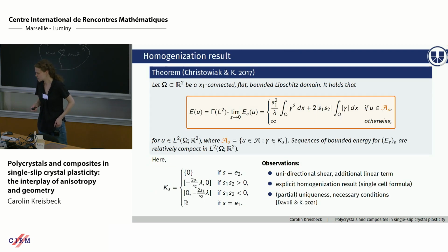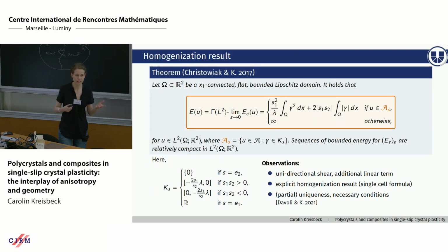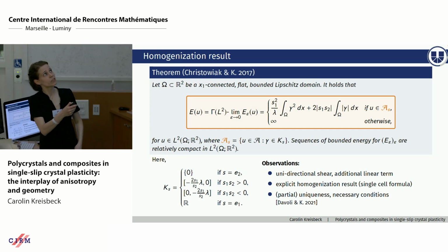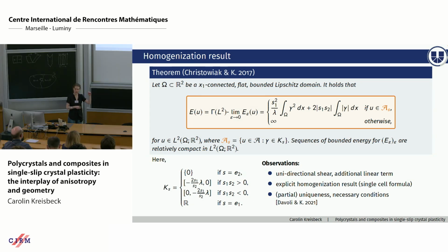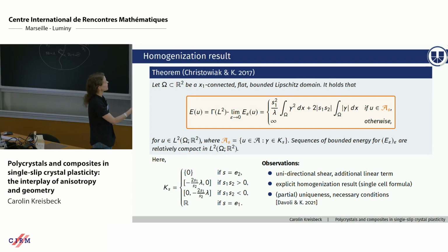So with this result as the main tool, we can then formulate our homogenization results in terms of gamma convergence, along with also the compactness that comes with it. So let's have a look at the gamma limit. It's finite on the set AS here. So these are the globally rotated shear deformations, and we can get additional restrictions coming from the orientation of the slip systems. So this is what this KS encodes.